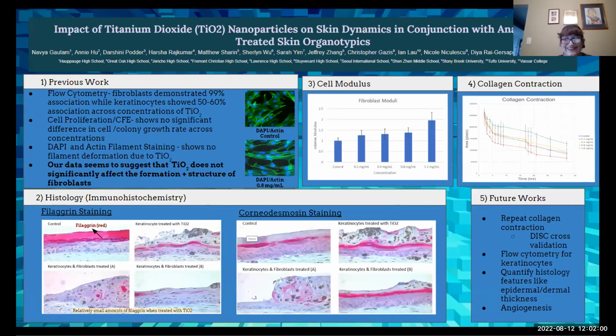So in order to examine the effects of TiO2 on the ability of the skin to contract and remain flexible over time, we plated fibroblast-laden collagen into well plates at various concentrations of TiO2. And over a period of 32 hours, we took images of the resulting gel as it contracted. Using ImageJ, we analyzed the area of each gel as it contracted in the well plate for every pictured hour. And what we found was that despite some slight variations, which we think were probably due to human error in the plating, generally we observed that for each concentration, the collagen contracted at very similar rates. So we can conclude that the titanium dioxide did not significantly impact collagen contraction.